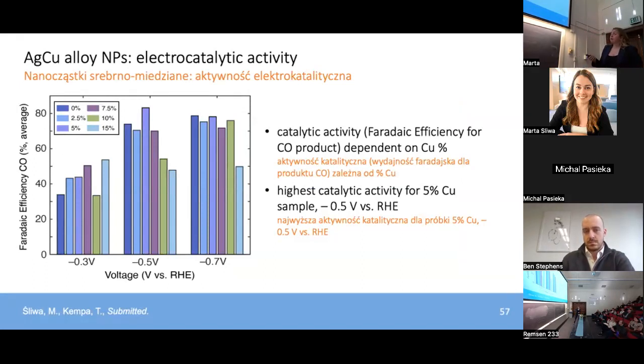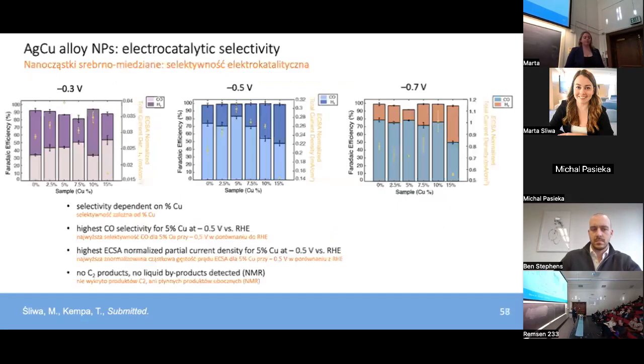We saw that the majority product for our process, with the CO2 reduction reaction on our nanoparticles, is the CO product, which is denoted by the Faraday efficiencies for CO in these bars here. We also saw a higher Faraday efficiency as we go to more negative voltages or overpotentials, which is unsurprising. But what is very interesting is that we have the highest activity for the 5%, so not the highest copper content, 5% copper and silver alloy at the middle, or moderate, voltage value of negative 0.5 volts versus RHE.